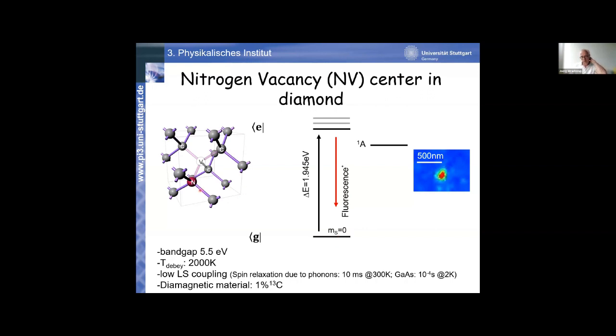Oh yeah, by the way, for those of you who haven't seen this, the nitrogen vacancy center actually comprises a nitrogen atom, which is at a carbon lattice site, and the nearest neighbor vacancy. And the way you do this is, for example, you implant nitrogen in a pure diamond, and then upon annealing, so if you heat up the crystal to 700-800 degrees Celsius or so, the nitrogen very easily replaces the carbon, and it bonds to a neighboring vacancy. So that is a chemically very stable bond, and this is how you form this NV center in the crystal.